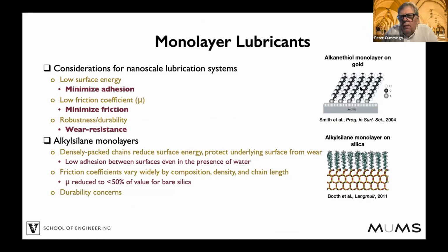Alkane thiol monolayers on a surface, alkylsilane monolayers on silica. Putting these things between two surfaces can reduce friction by half or less compared to that of bare silica.